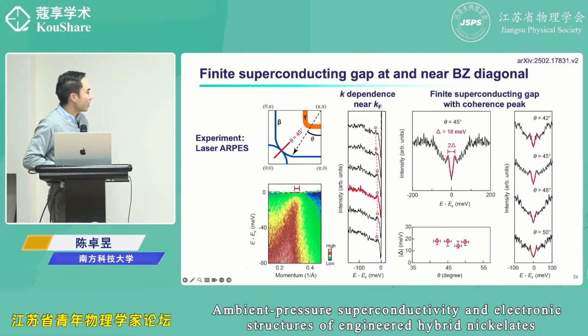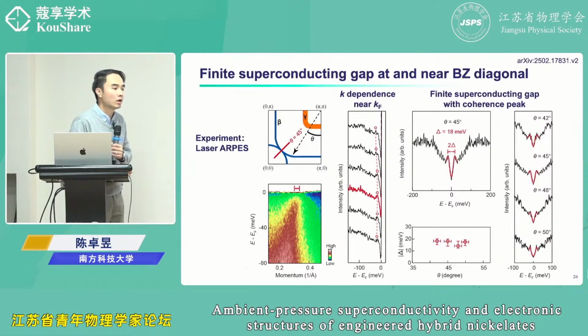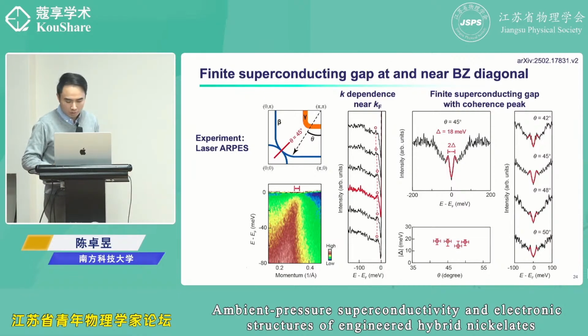Another feature is this backbending. Usually, if it is a superconducting gap within a finite range of momentum near kF, you should see a backbending, and we can also see this backbending. Also, within a range near this 45 degree, we see this superconducting gap with the coherence peak in all these cases, from 42 degrees to 50 degrees. This set of data was obtained in Junfeng's lab at USTC with the laser ARPES. Temperature dependence, I have a slide. Yeah. So laser ARPES has very high resolution, but it has no access to the boundary of the Brillouin zone.